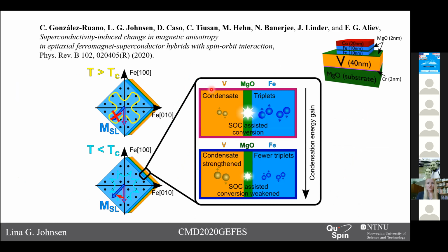Next, I want to mention a work done together with our collaborators led by Farkhad Aliev. This is an experimental work mainly, where they found a change in the magnetic anisotropy of a vanadium magnesium oxide iron system due to the superconducting phase transition. As is sketched in this figure, for temperatures above the critical temperature, we have minima of the anisotropy in the directions of the cubic axis, so that the magnetization prefers to stay along the cubic axis.